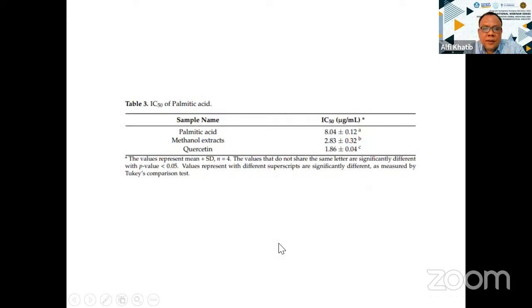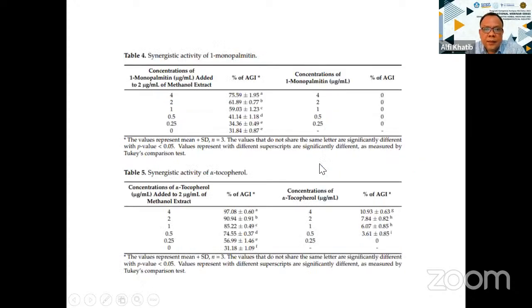Okay, so now when you go here, the last time we found the palmitic acid is the one which is active. So when we check, you buy the standard and you find that this one is active, in line with our metabolomics finding. But then when we try monopalmitin and tocopherol, they're not active. So why are they not active? This is what you will get if you go to the bioassay approximation. Monopalmitin is not active, and tocopherol is also not active, but metabolomics says these are involved in the activity. So why are they not active?